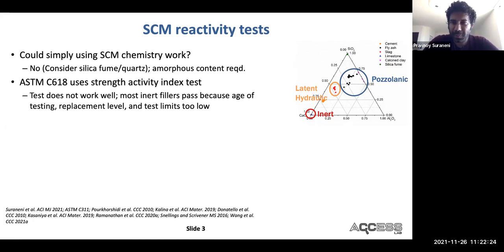The ASTM C618, which is the standard for fly ash and natural pozzolans in the US, uses the strength activity index test. The way this test is set up in ASTM C618, it simply does not work. You can use it, but it's not going to tell you anything about your material. So even inert fillers will pass this test because it's tested at 7 days, and at that time, you don't really see much reactivity from low reactive materials.